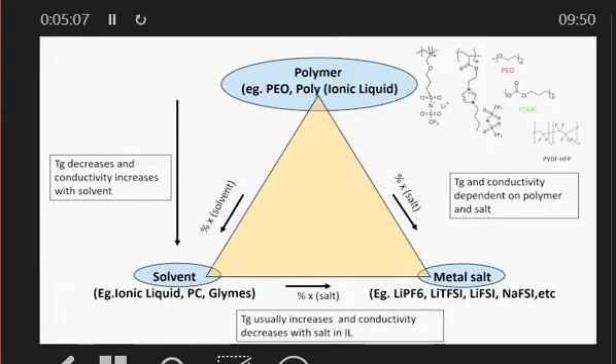And then we have a polymer where we add salt. Now, the polymer can be either a neutral polymer, traditional polymers like PEO, polycarbonates, where we add salt, and we find, again, a large composition range. We know that the conductivity, the Tg, all these are affected by this composition. And then we also have the possibility of having all three of these things: the polymer, the solvent, the salt, to control the conductivity, the mechanical properties, the glass transition temperature, the stability, all those things are available to us.